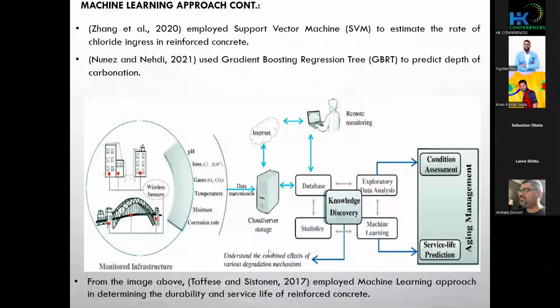Just like I have on the screen here, these are the researches that have been conducted over the years in utilizing machine learning approach in determining concrete durability. The first one is Zhang et al., which employed support vector machine to estimate the rate of chloride ingress in reinforced concrete. We also have Nunez and Nehdi, which used the gradient boosting regression tree to predict depth of carbonation. And this big picture here was conducted by Taffese in 2017, which employed this approach in determining the durability and service life of reinforced concrete. So all of this setup that we see, the aim is to determine the durability and service life of reinforced concrete. So let me next my slide.